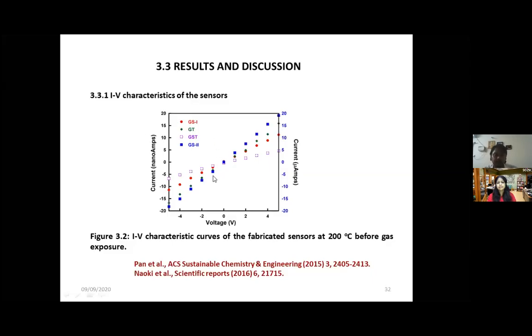So here there are differences in sensor response from GS1 to GS2. See, for GS2 alone it is in microamps, for GS1 and all other 3 materials it is in nanoamps. So when we compare the resistance of these 2 materials, for GS1 it is in mega ohms, 450 mega ohms approximately, and for GS2 it is 250 kilo ohms approximately. So this change in resistance is attributed to the structural characteristics which you have seen.